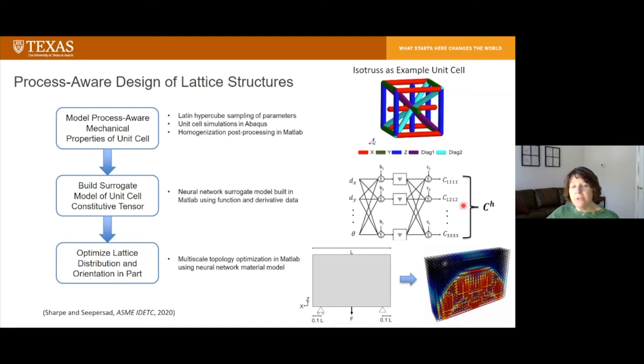We use that information to train a neural network surrogate model that can take as input the diameters of the different struts and produce as output the elements of the constitutive tensor that basically governs the mechanical stiffness of these unit cells. Then we take this neural network model and we input it into a topology optimization routine, where we can then take a domain, an arbitrary domain with loading, like in the case of this example, and then we can convert that into a lattice structure. And we can look at that and we can assume that these unit cells are process agnostic, so it doesn't matter whether the struts are horizontal or vertical or how they're oriented, or we can take that information into account.